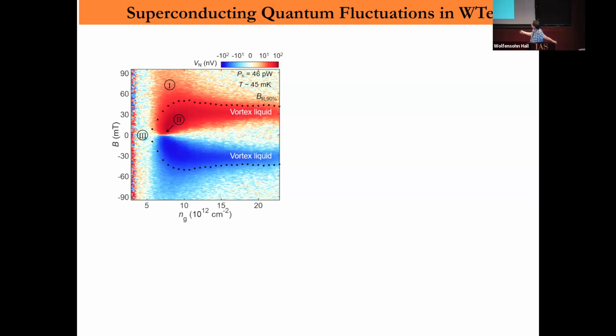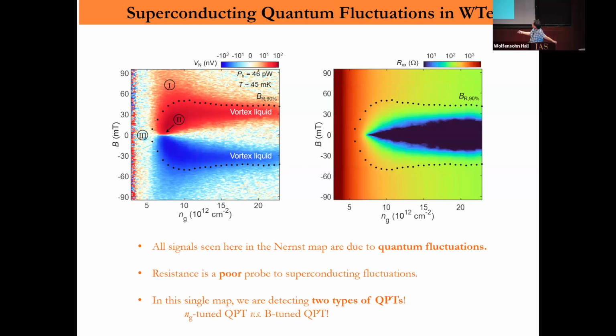And I can do a contrast between this map, which is the Nernst effect, a fluctuation, versus the resistance map. This resistance shows both the same thing, magnetic field and density. What we see is zero resistance here, where you also have zero Nernst effect, which means there's no vortex, or the vortex is not moving. But if you look at the resistance map, you don't have much going on here. It's not changing, it's just flat.